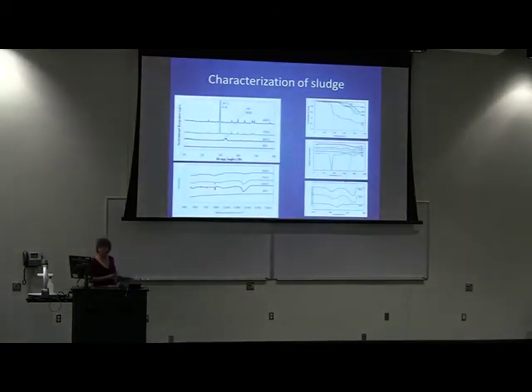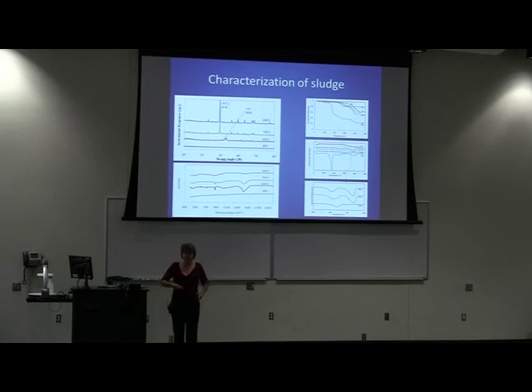I won't go through too much of this, but X-ray diffraction, I just want to give you an idea of what's available here at Miami when you do research. X-ray diffraction allows you to look at crystal structures in materials. And through the library, this peak here is calcium carbonate. If we heat it up to 900, the calcium carbonate goes away. It goes to calcium oxide.